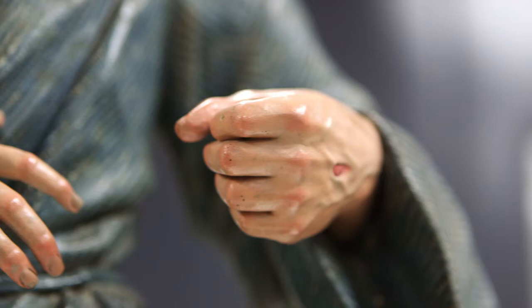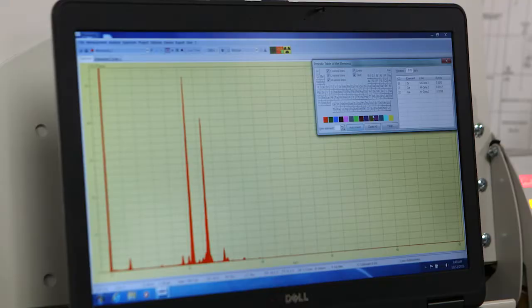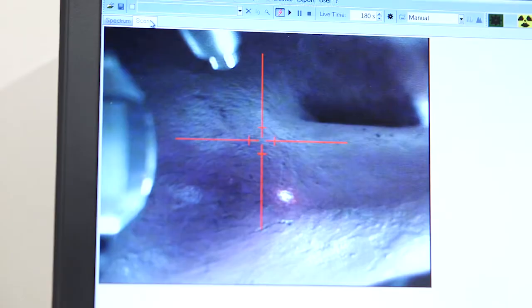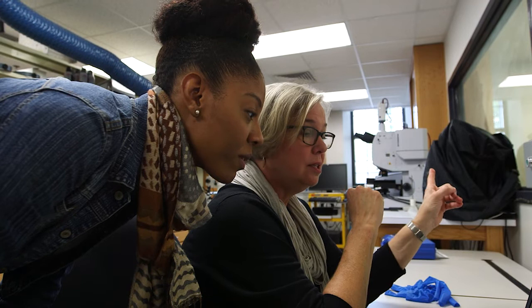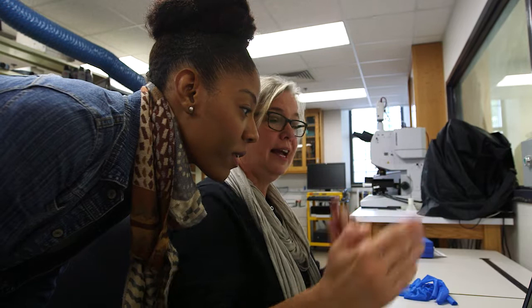We're looking at Saint Francis's knuckle and we're trying to figure out which pigments are present. When I see this sort of pattern here, they indicate the presence of lead. But then there's this one here — very close to the lead peaks but very distinctive — indicating the presence of mercury. This is primarily lead white with the presence of mercury to give it that pinkish hue. The mercuric sulfide red would have been mixed with lead white to create the pink surface of his knuckle. And if we look at the knuckle, you can see that it's pink.